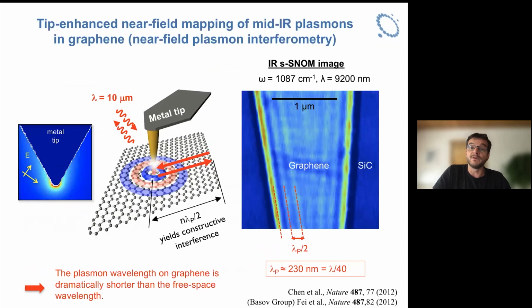And this is where we use a near-field microscopy technique that was originally intended to perform chemical imaging, but it turned out that it's also a highly interesting tool for mapping these exotic electromagnetic waves. So I briefly outline it here. The microscope is basically an atomic force microscope where we use a metallized tip. Then we shine light onto the tip. The tip acts as an antenna. It converts these propagating modes that arrive at the tip into highly concentrated near fields at the very tip apex.